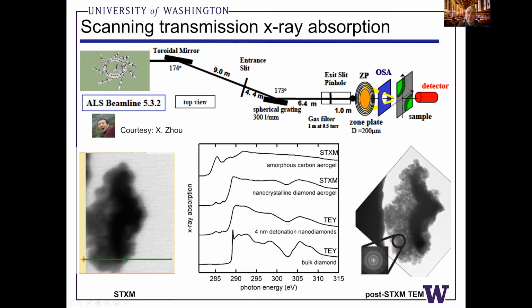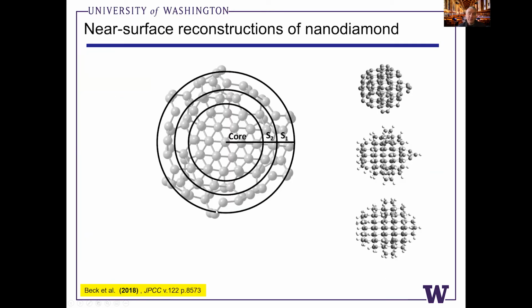This is a spectrum from detonation nanodiamonds. This is a spectrum of bulk diamond materials. So this is some additional evidence that we have a phase conversion from amorphous carbon to diamond. But interestingly, there's some pre-edge features that also index to a graphitic type of microstructure. And we weren't quite sure what would explain this type of surface reconstruction.